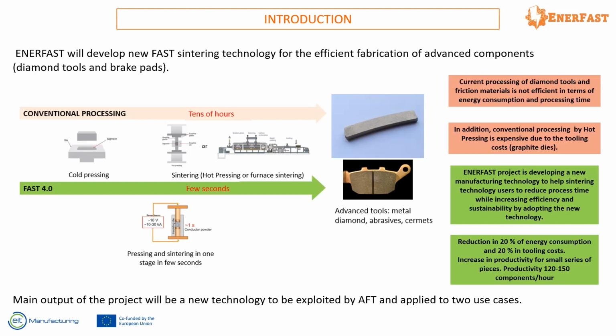As you will see, as it's for hours in a furnace at more than 1000 degrees C, this process is very energy intensive. The consumption of energy is very high and very ineffective. They say that only 30% of the energy you put in is really used to heat the material, and the rest is energy that is lost during processing. Here in ENERFAST, what we are trying to implement is a fast processing, and the difference is that you put a material in a die, you press it, you cross electricity through the material, and only the material is heated. This is the important part here. As we are only heating the material itself, we are not losing all the heat to the outside as in the conventional process. This is probably the main advantage of this ENERFAST process.